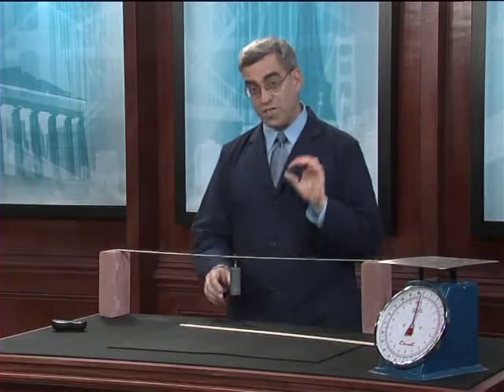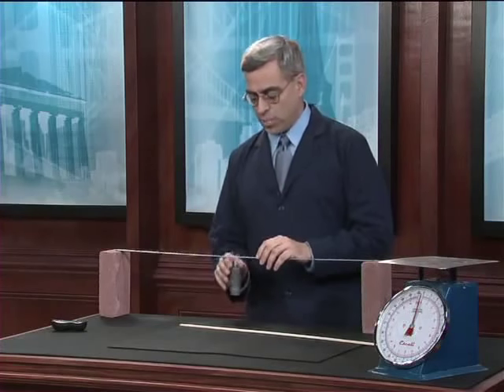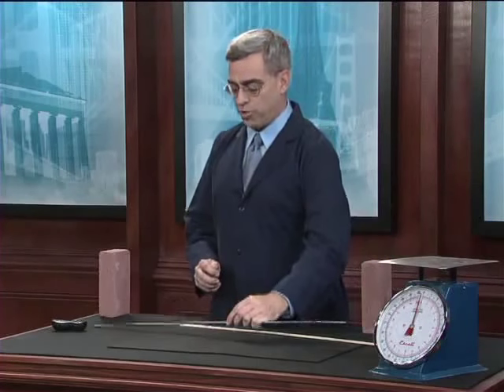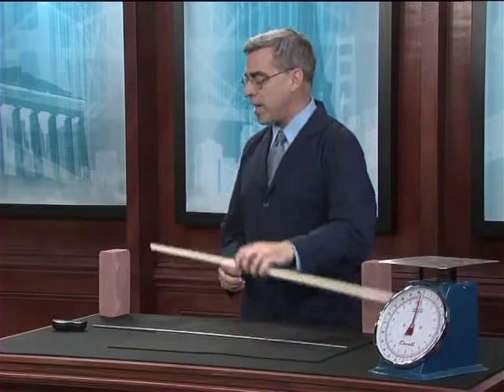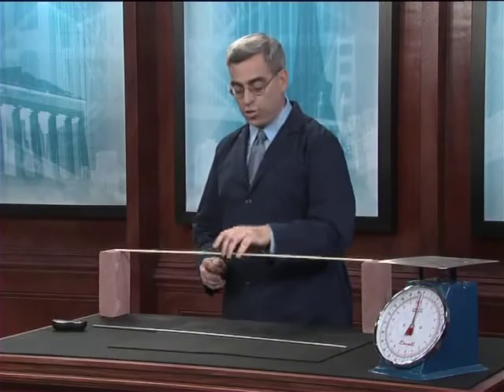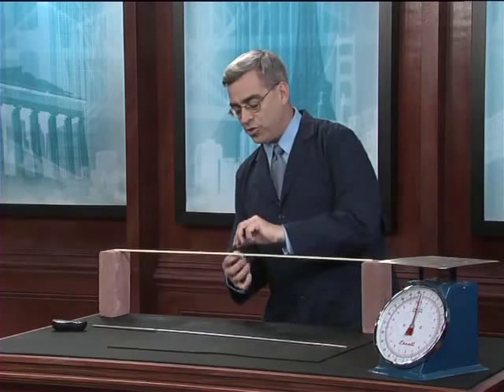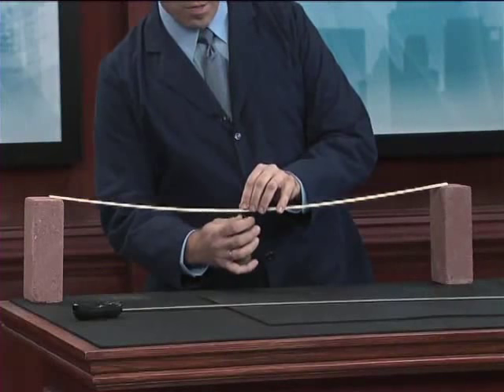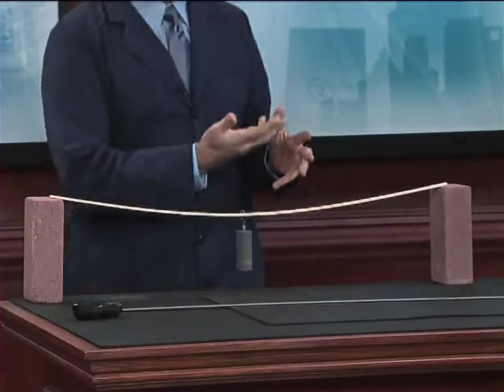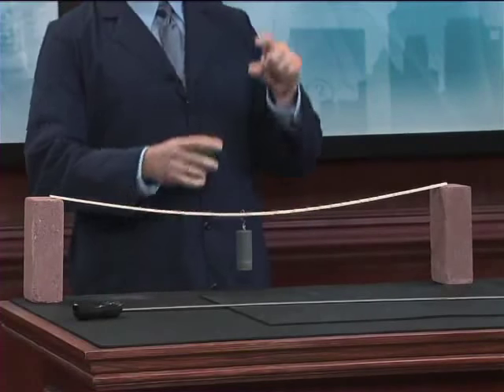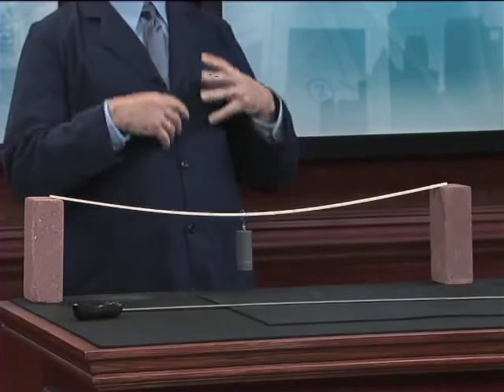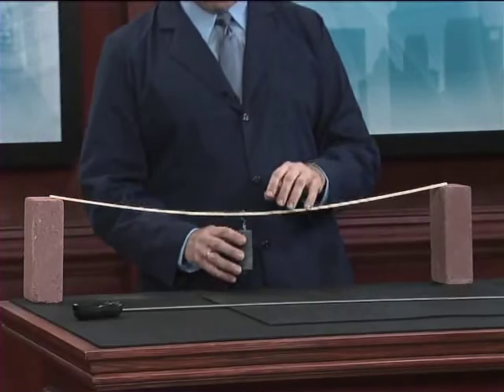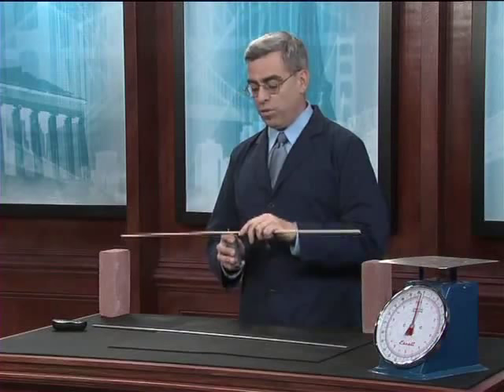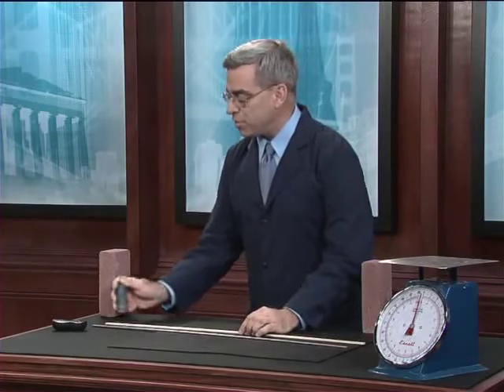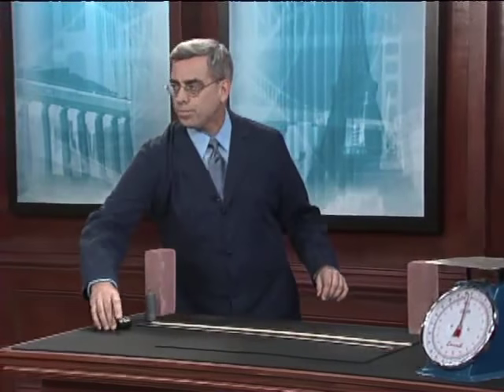That's a pretty good reflection of the stiffness of steel, its capacity for resisting elastic deformation. Now, if I do exactly the same test on the wooden member, which again, remember, has identical dimensions, we find that those flexural deformations, the bending deformations, are in excess of 2 inches, more than 20 times larger than the deformations that we saw in steel. So clearly there is a vast difference between the stiffness of these two materials as well.